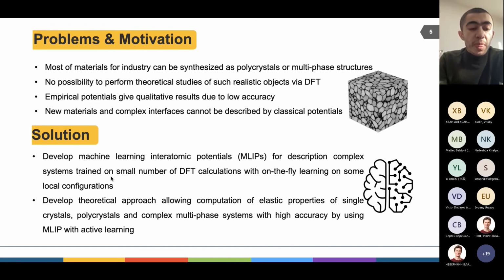They do have good accuracy. And also classical empirical methods are able to describe such systems, but the accuracy of calculation is rather low. Moreover, in polycrystals, there is an interface between grains that does not have a crystalline structure, and describing the grain boundary exactly is a difficult task for empirical potentials. And to solve this problem in our project, we developed an automatic algorithm for calculating the main mechanical properties of polycrystalline materials, where the interatomic interaction is described by machine learning interatomic potentials.